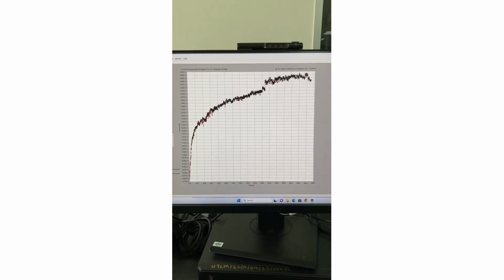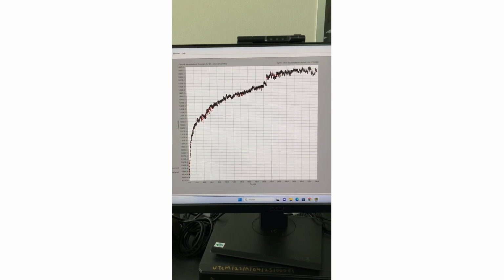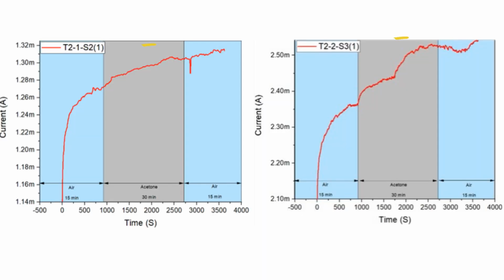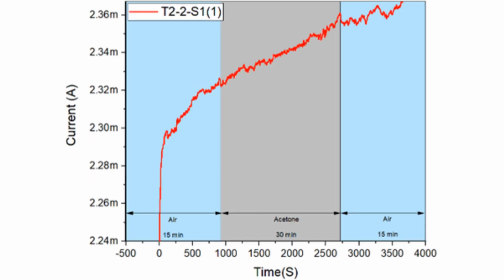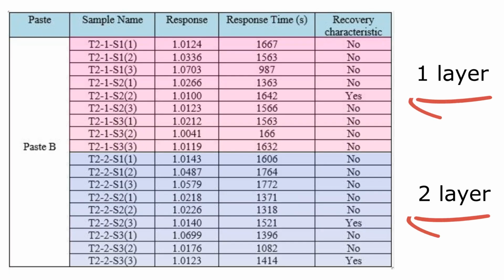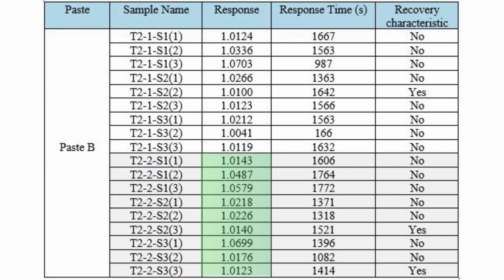The glassware hose was withdrawn from the gas chamber after 30 minutes and the recovery time was recorded for 15 minutes. Among them, T21 sample 2 and T22 sample 3 showed saturated current when exposed to the acetone vapor, while other gas sensors were unable to saturate in 30 minutes. The double layer was significantly greater than its single layer, with a consistent response within the range of 1.0123 to 1.0699. The greatest response value is 1.0703 and the lowest value is 1.0041.